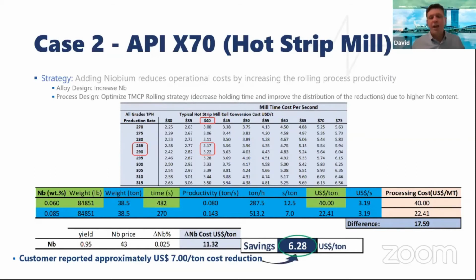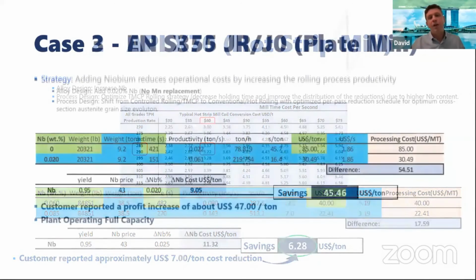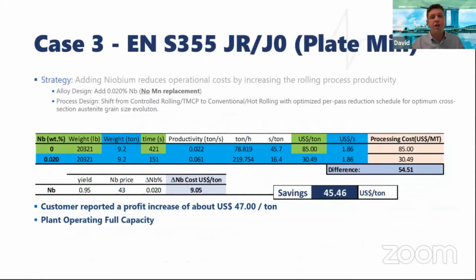bringing a 6.28 calculated cost reduction, but actually our customer reported approximately $7 per ton, which is pretty close to the calculation, but better. Case number three, it's a 355JRJ0 chemistry, which used to be completely carbon manganese, no microalloy. It used to have a 78.8 tons per hour productivity.